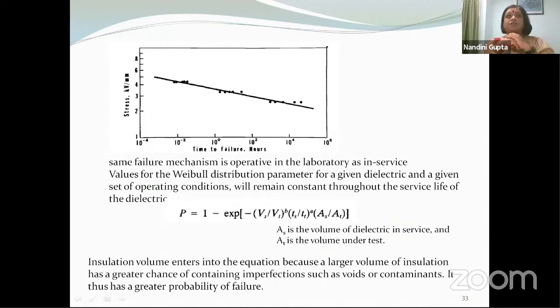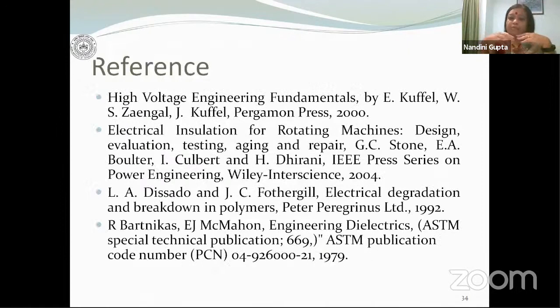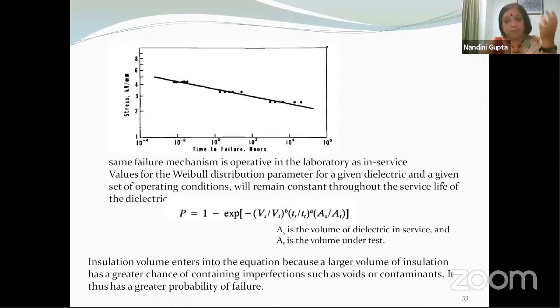scale accordingly. To give you an intuitive feel why the volume matters, if you have a large amount of insulation volume, it is likely to have a higher probability of having damage mechanisms, defects, the possibility of having voids, the probability of having traps, trap levels are much higher. So the higher the volume of insulation, the more likely is failure. And therefore, it is important that we scale the outcome of the regression analysis with the ratio of the volumes of insulation under test and in service.